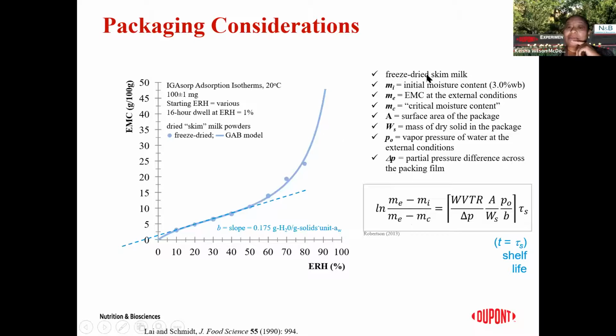So for example, if I took my freeze-dried skim milk powder, I know what the initial moisture content is. That is, I took that from the final moisture content coming out of the freeze dryer. I would define what the equilibrium moisture content is at the external conditions that are of interest to me. So for example, if I want to store my skim milk at 50 degrees C and 50% RH, I would have those definitions. I would also have to define what my critical moisture content is. That is, for example, am I storing this milk in a place where the milk is going to start to smell? So after a certain time or temperature, the milk will start to smell or what have you.